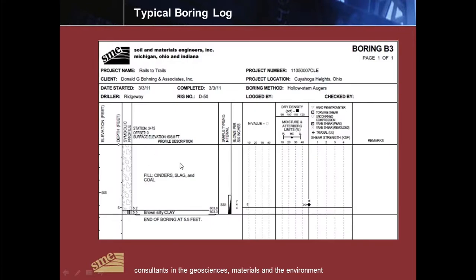Our subgrade was a railroad ballast that was placed in the early 1900s. Back at that time in the greater Cleveland area, they used a lot of cinders and slag mixed with coal and other building material. This profile here is fairly standard throughout the section. There's about 5 feet of this fill, and it's placed over a soft to medium consistency clay. Generally, the fill material was dry. We have not seen groundwater accumulating in the base over the top of the subgrade.